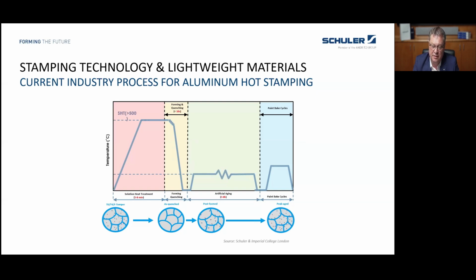So you have to run it through the next process, which is the artificial aging of the material. That means you put all the parts in a chamber furnace, and then you run it somewhere between 100 and 150 degrees Celsius. You have it there, depending on the material, somewhere between 3 and 8 hours to create this artificial aging process, and then the material is hard again. It's followed by the paint bake cycle, which is normal for the automotive industry. That means when the car body is manufactured and painted, drying the paint is also a heat treatment which has to be taken into consideration for the complete aging process. So the end product is again a high-strength aluminum part.